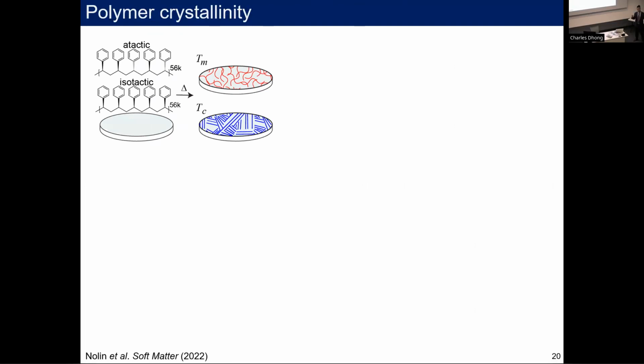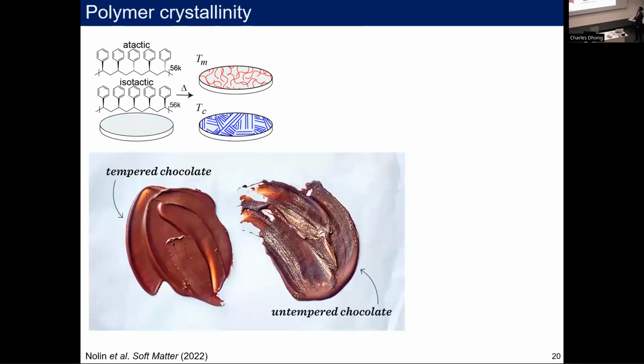So kind of going back to the materials discovery, I think what we've shown is kind of a pipeline. How would you actually then discover new materials and use this for a broad range of phenomena? So earlier we found that monolayer ordering is a source of tactile contrast, but now we can start to apply this to polymers, right? If you think about long-lasting durable materials, polymers fit the bill. So here we've created different surfaces with the same chemical formula, but different levels of crystallinity in the polymer. So one way is through annealing at different temperatures, and another way is by varying the tacticity of the starting polymer. So this isotactic one is more likely to form crystalline domains.